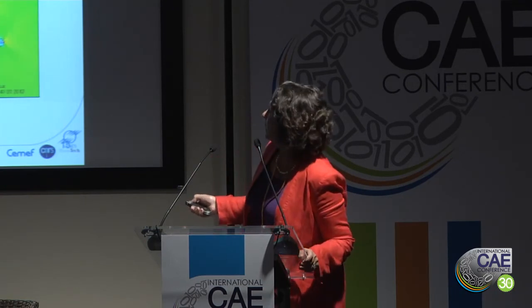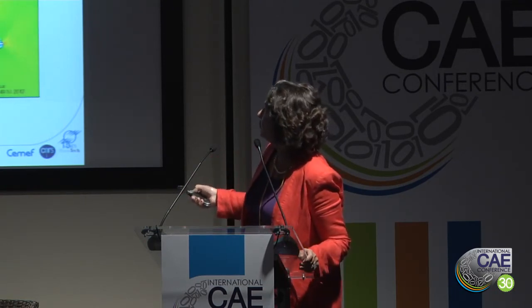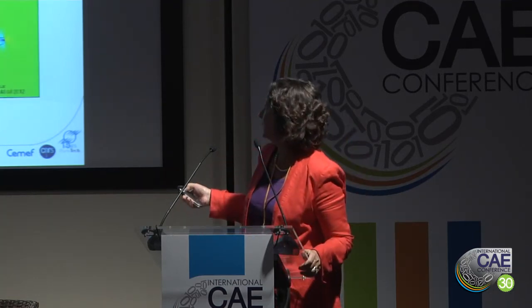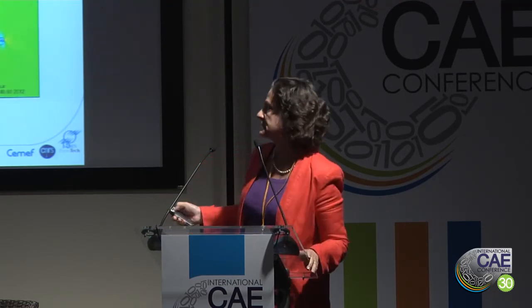Okay, so another example is here with the two methods. We applied a tensile test on the sample with some inclusions, and we have the different behavior of the material. It's very important to notice that the gray part is also a mesh. So everything is meshed. It's the same mesh. We just refine the interface of the different parts. So you can see here the interface of the inclusion and the matrix, and here the void appearing, and the void is also meshed.